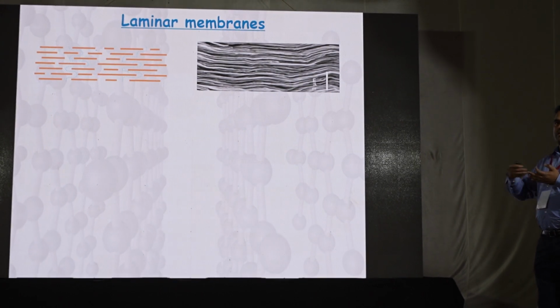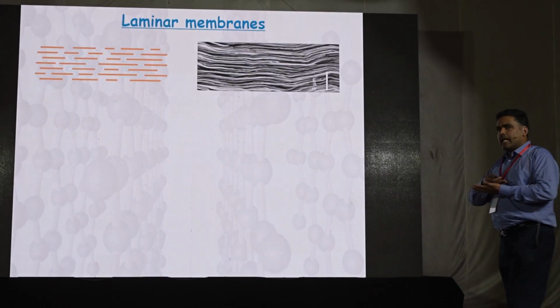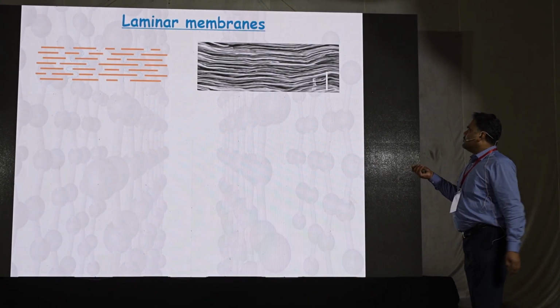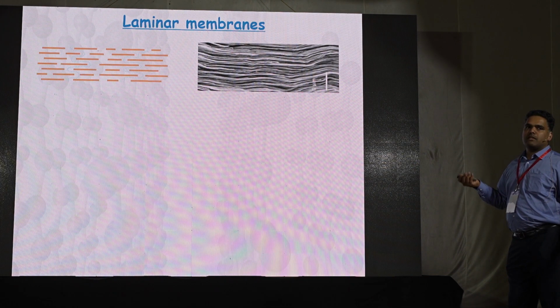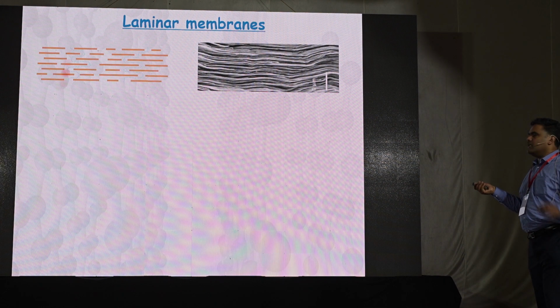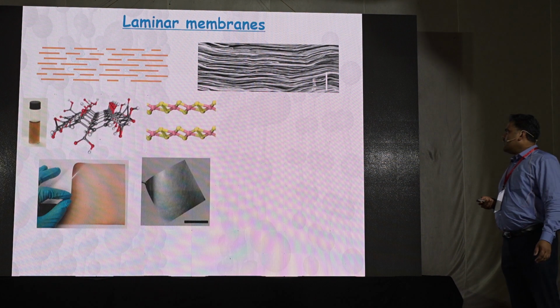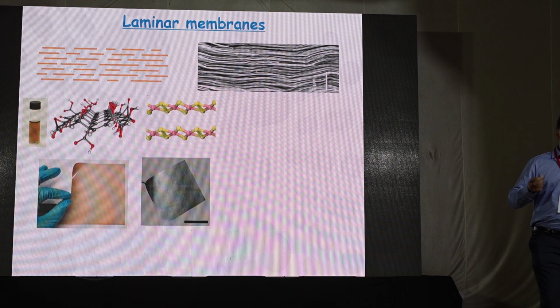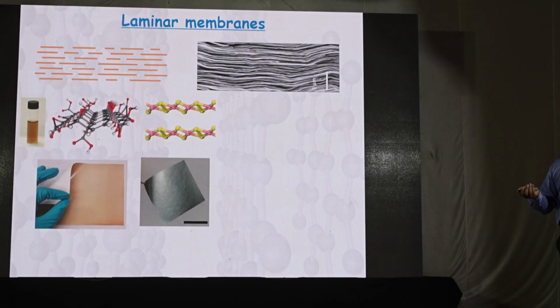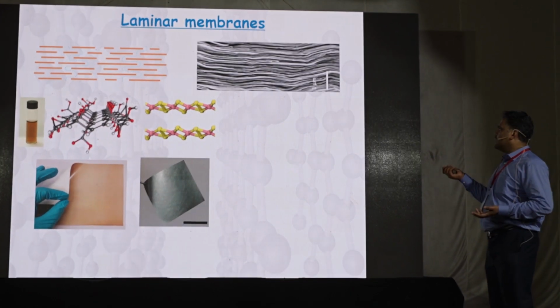So each layer is randomly ordered, and we are using the spacing between the layers as a pore to design a membrane. And depending on the pore size, depending on the spacing between the layers, you create different membranes. This can be done using different 2D materials. It could be graphene oxide. Graphene oxide means it's an oxidized form of graphene with several oxygen functionalities on the surface.